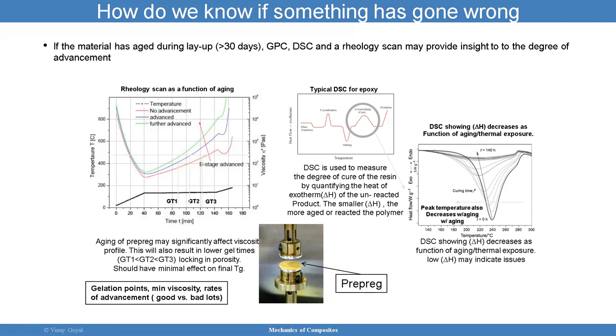And you may ask me, what is DSC? DSC is differential scanning calorimetry. It's a machine that allows you to perform a thermal analysis to determine the degree of cure, the glass transition temperature, and the melting point of the composite material. Those are good things to do to really understand the quality of the material as you move forward. Okay, so that's some of the things that are done.